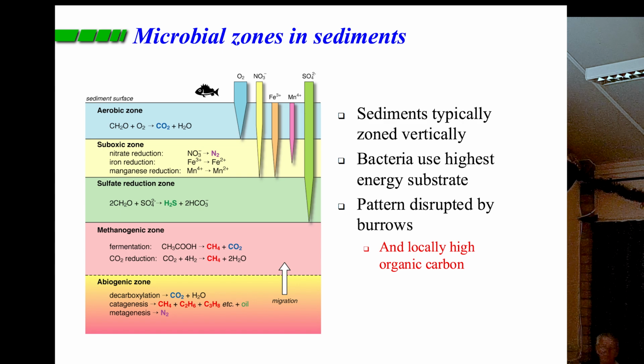And then at greater depth, when there's no oxygen left, no iron oxides and no manganese oxides, the bacteria resort to the next best thing, which is sulfate. What they do is take the oxygen from the sulfate to oxidize the organic matter. That results in the formation of hydrogen sulfide, the rotten egg smell, and also releases bicarbonate species, which can lead to cementation by calcium carbonate. So in the centre of this Bathichnus paramoudrae, clearly we've had a lot of sulfate reduction occurring locally where the paramoudra is, but nowhere else.